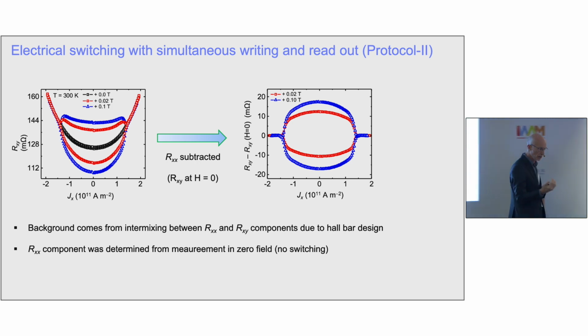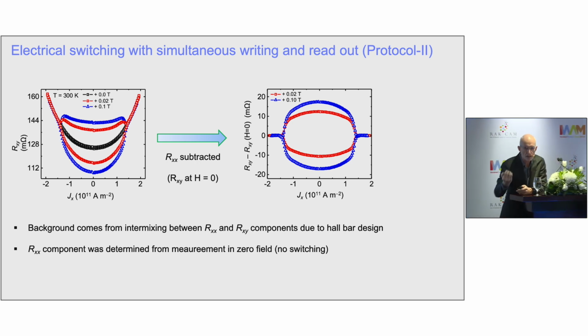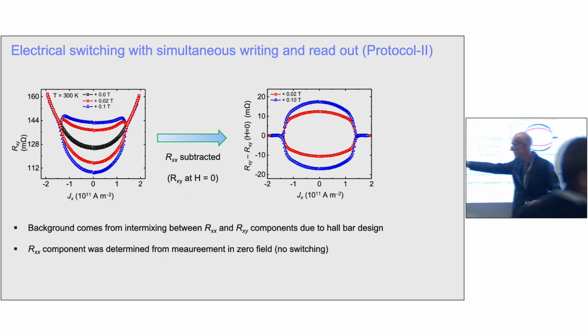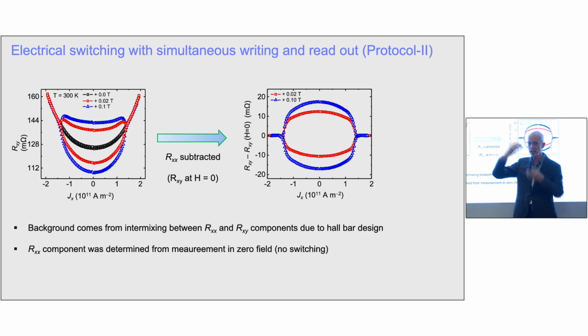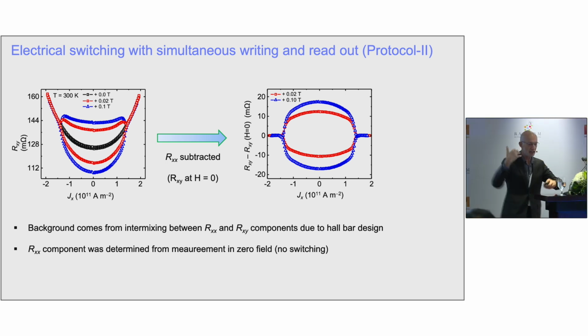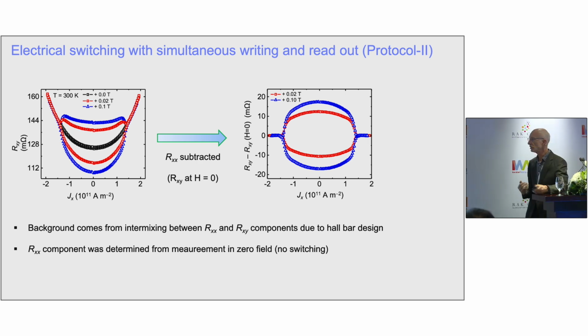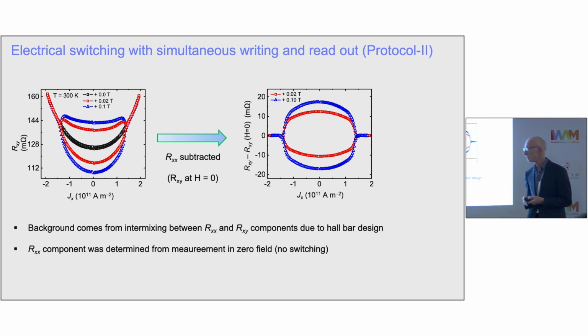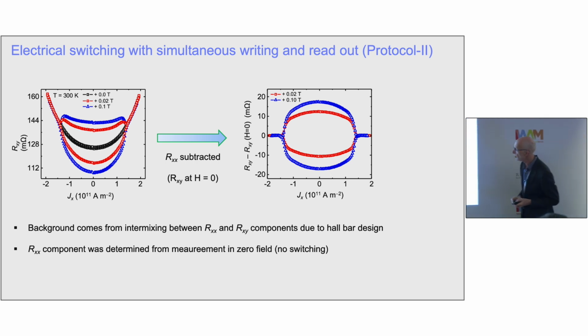And the reason for this is the system gets very hot. So it's actually heating up, which is why this resistance is increasing as we increase the current. So it turns out that we believe there's a very significant contribution to the manipulation of this structure from heating through the same current pulse that is generating the spin current to manipulate it. This is what we find.